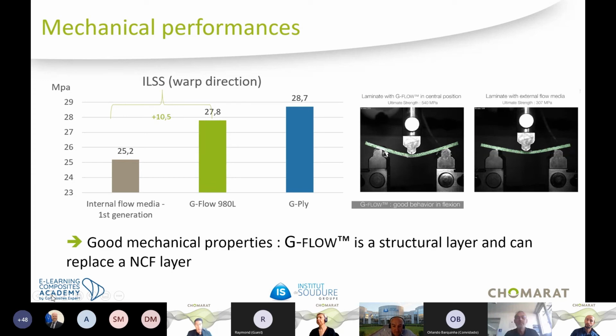In blue, you have a laminate made only with standard NCF, the brand G-Ply from Chomarat, plus an external flow media. In gray, you have a laminate with an internal flow media first generation, which was not at that time a 100% glass, but a mix between glass and thermoplastic. And then in green, you have the G-Flow, the structural flow media 100% glass. This showed that a laminate done with G-Flow brings the same properties as a laminate done with glass fabric NCF. And the G-Flow can replace a layer of this reinforcement.